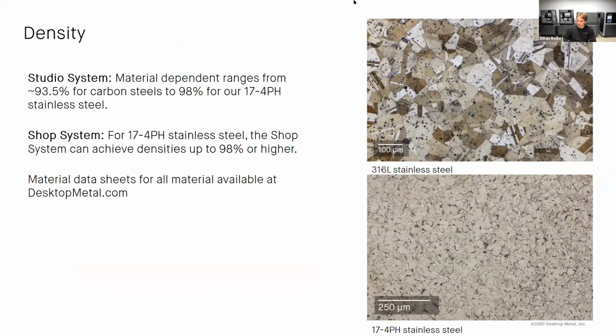Looking at density on the Studio System, the material density is really dependent on the actual material. For some of the carbon steels, we're seeing about 94, 93.5%, looking to increase that constantly. But when it comes to 17-4 PH, which is the first material that we released on the Studio System, we're now consistently seeing over 98% dense. So that's the density that you really need for your prototypes and for those replacement parts.